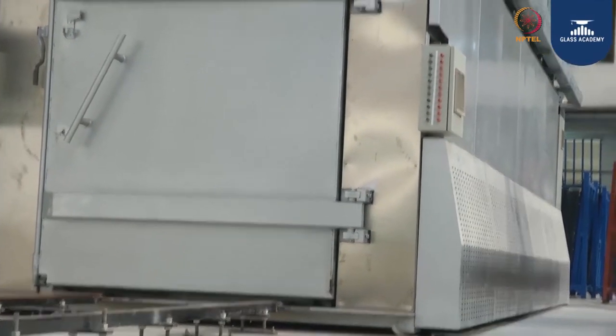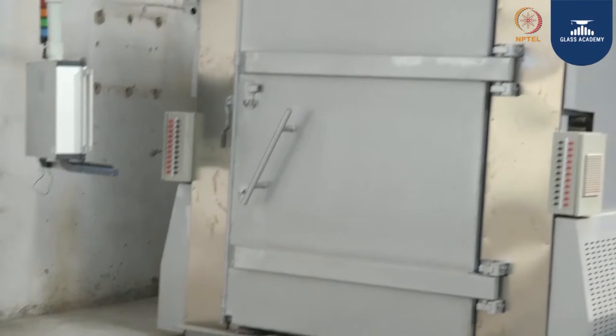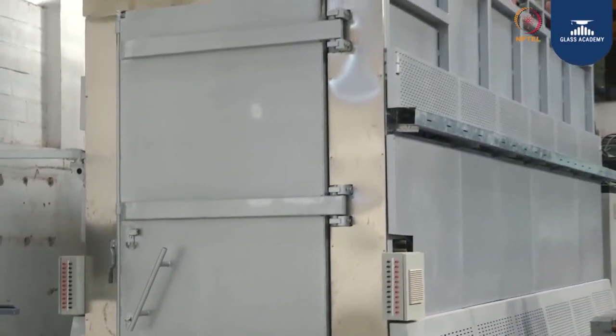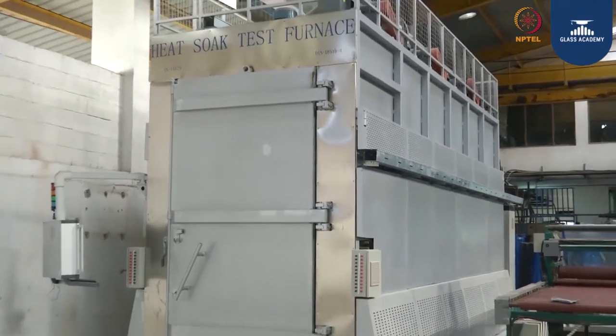In order to minimize the spontaneous breakage, the toughened glasses are sent inside the heat soak chamber. This works similar to an autoclave, where the glass will be heated and held at 290 degrees centigrade and again cooled. This is a complete 6.5 hour cycle.